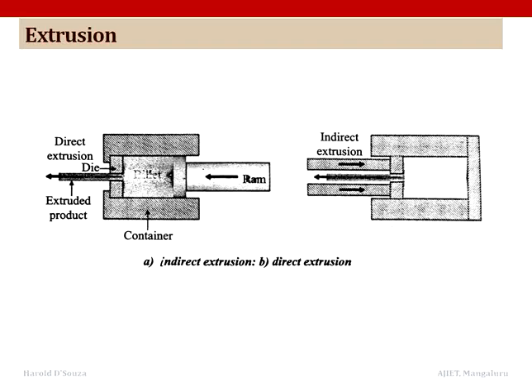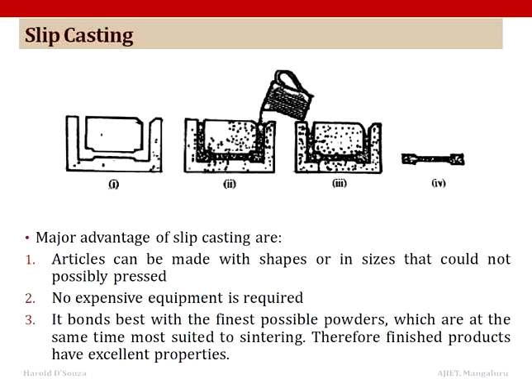Now, the extrusion pressing of sintered materials such as high speed steel or superalloys, where almost porousness structure can be achieved, or we say sintered materials dispersion hardened by the oxide, is very effective. Now, the used cans oxidize during the process, so they are removed from the compact by stripping or possibly by chemical etching. Slip casting. Slip casting is frequently used for compacting metal and ceramic powders to make large and complex shapes as well as for limited production runs.